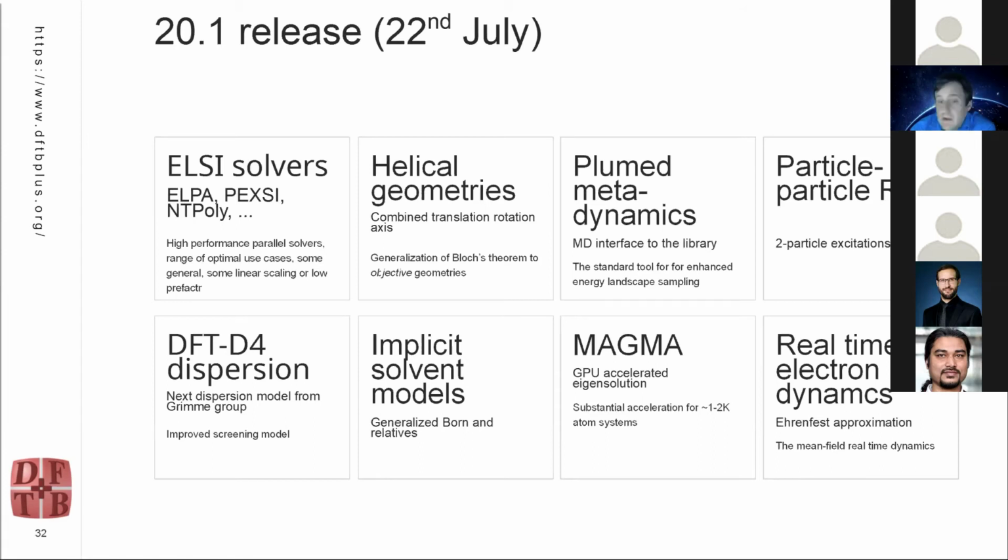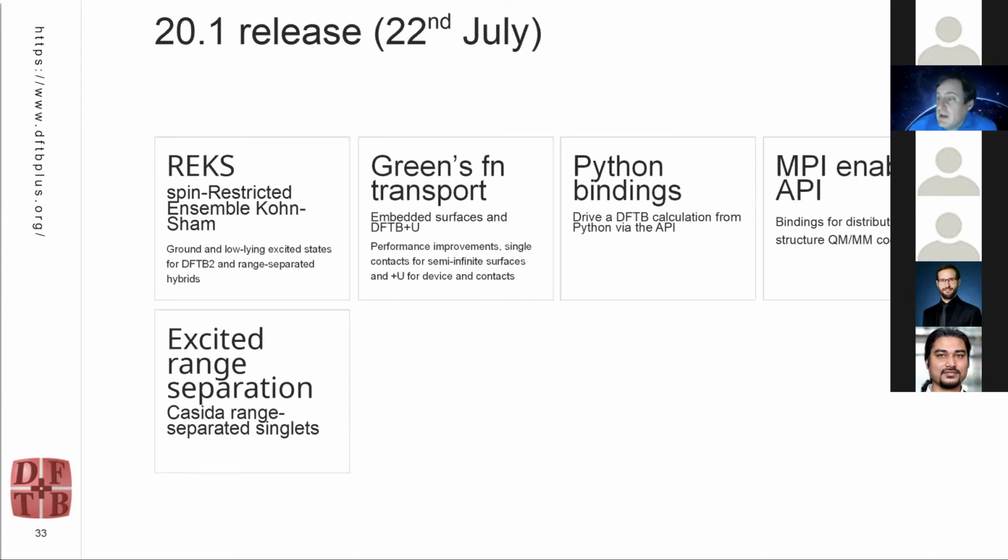look at systems. Okay, we also have, and again, this is a way to get into, for example, some information about excited states, what are called spin-restricted ensemble Kohn-Sham methods. So this is, for example, the group in Busan, South Korea, who have contributed this, and it gives a way to have a look at states which are actually more like the kinds of wave functions that really are present instead of the approximate Kohn-Sham-like states. So you build an ensemble of these things and solve for these kinds of cases. And they've also got hybrid functionals as part of that calculation methodology.